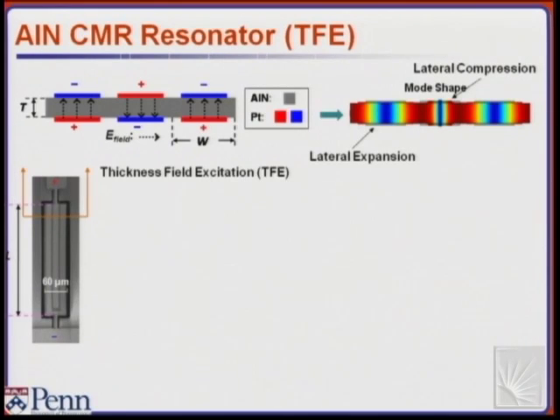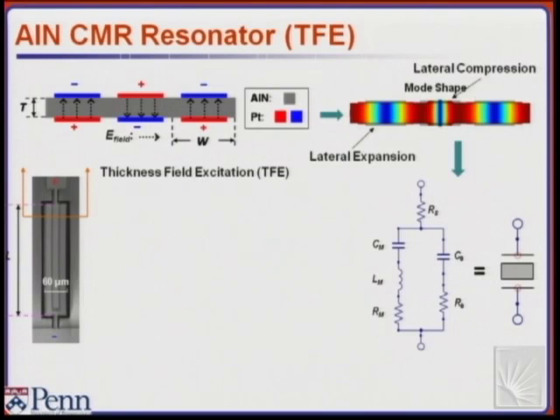If you use a 2D model, things get a little bit more complicated and you need to take into account a real plate at that point. But still, basically you have lateral expansion and compression, and that can be modeled as a standard quartz crystal device or a mechanical resonator, same thing that you do at the millimeter scale. This is a slightly modified model that takes into account parasitics that tend to play much more of a role at the micro and especially at the nano scale. So the external parasitics actually can become comparable to your device size and can cause a problem. So you need to account for those.